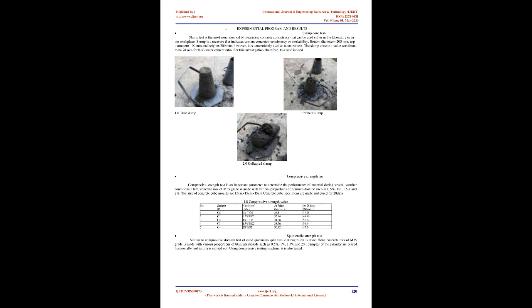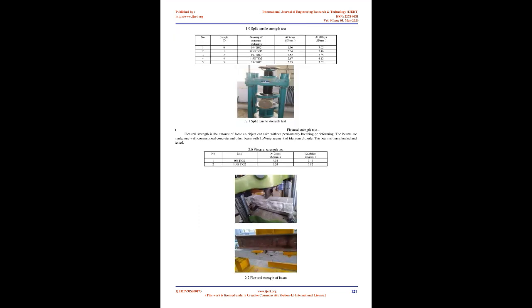Slump cone test. Slump test is the most usual method of measuring concrete consistency that can be used either in the laboratory or in the workplace. Slump is a measure that indicates cement concrete's consistency or workability. Bottom diameter equals 200 mm, top diameter equals 100 mm and height equals 300 mm, however, it is conveniently used as a control test. The slump cone test value was found to be 78 mm for 0.43 water-cement ratio. For this investigation, therefore, this ratio is used.